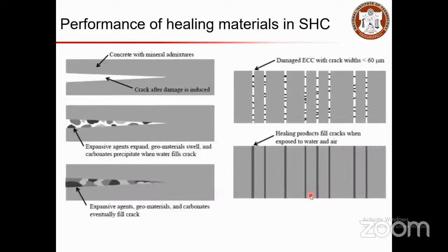So if you look at the external categories, the performance of healing materials in self-healing concrete is that you can have some concrete with mineral admixtures. The crack after damage is induced, and then now you can see the expansive agents. You can see some geomaterial swell that can eventually swell and fill up the crack, and these expansive agents and geomaterials eventually fill the crack completely.